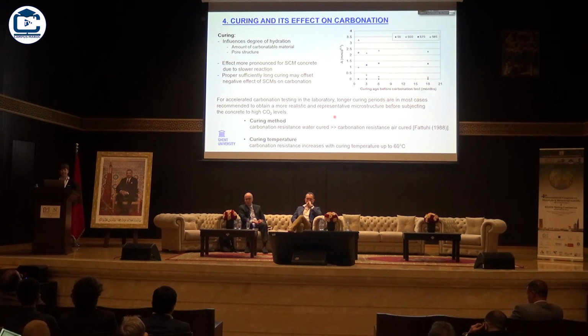What about curing effects? More curing will of course densify the microstructure. So that's the most important effect, that more curing will slow down the carbonation reactions. And actually, a sufficiently long curing may offset the negative effect of SCMs on carbonation because of the reduced buffering. Like I mentioned, for tests in the lab, you really have to take into account that you do not concentrate all your carbonation at an age when the microstructure of the concrete with SCMs is not fully developed yet.